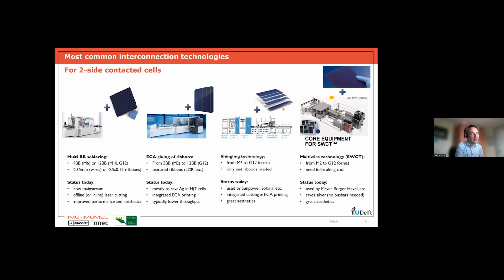And then something else which is also being done is so-called multi-wire technology, for instance, like Meyer Burger is doing. So here you don't need bus bars on the cells, but you just have the fingers. You then use a foil which contains wires to interconnect neighboring cells. And again, that gives a very nice look. So it's a very even look. You don't see the bus bars and the copper ribbons anymore because they are not there. So again, it gives great aesthetics, and it also saves some silver. So it's a very interesting approach.